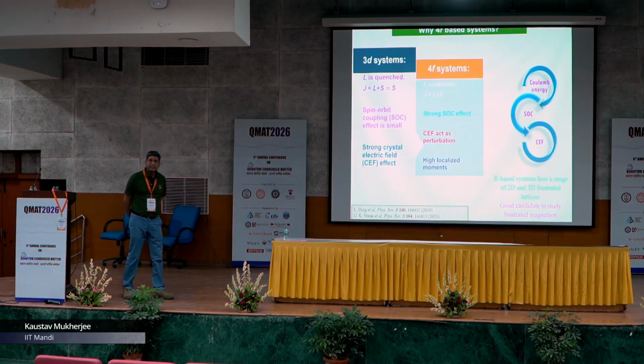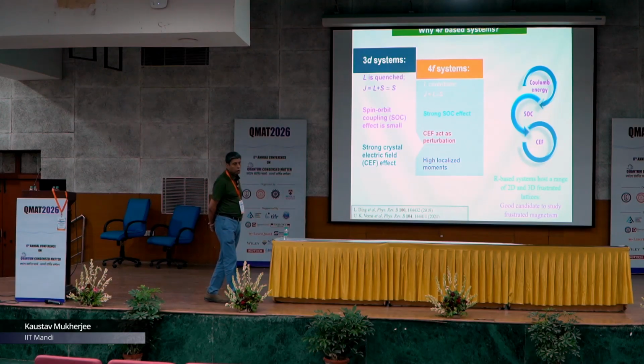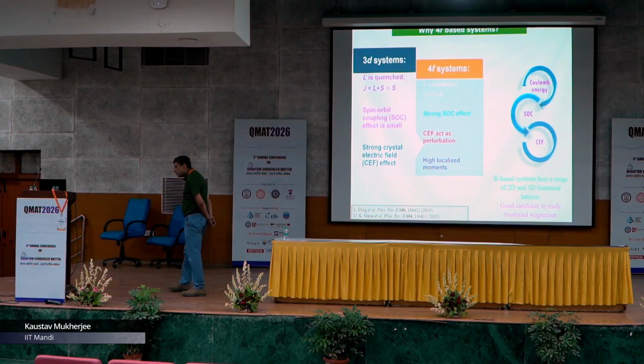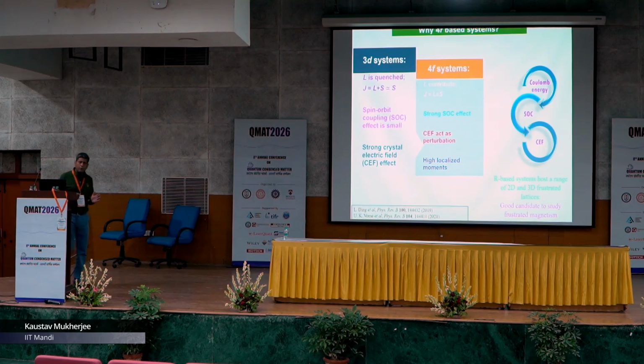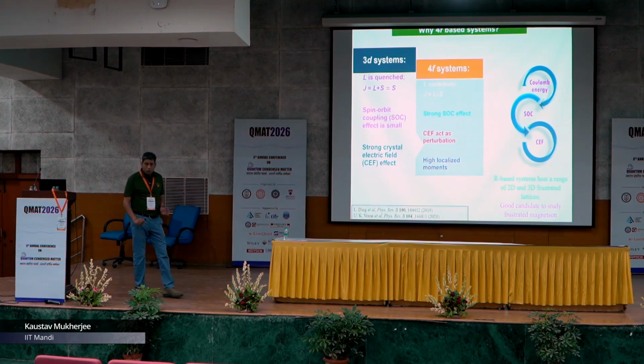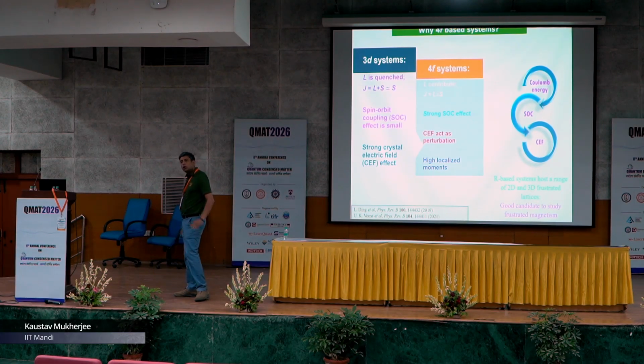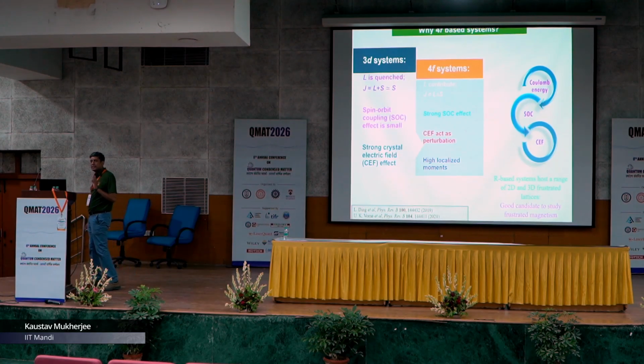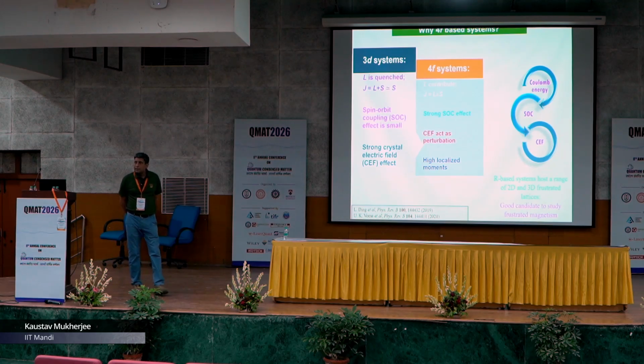In contrast, for 4f systems, the orbital angular momentum is not quenched, and the total angular momentum arises from the combination of both the orbital angular momentum and the spin angular momentum. So in this system, there is a strong spin-orbit coupling. In 4f systems, the crystal electric field also acts as a perturbation, and as we all know, 4f moments are localized moments as compared to the 3d moments. So in one sentence, it can be said that in 4f systems, Coulomb energy, crystal electric field, and spin-orbit coupling play a very important role in defining the properties of the system. So briefly, rare earth based systems host a range of 2D and 3D frustrated lattices, and these rare earth systems in such lattices are good candidates to study the topic of frustrated magnetism.